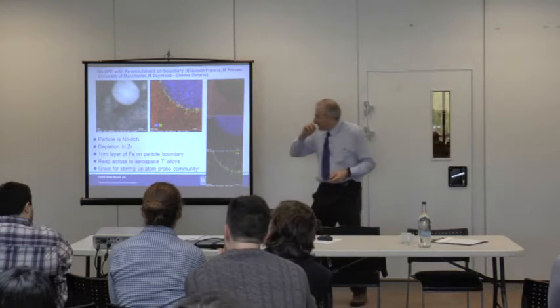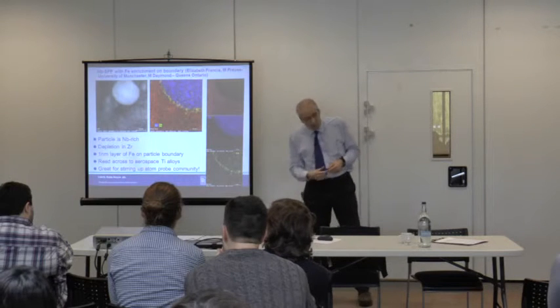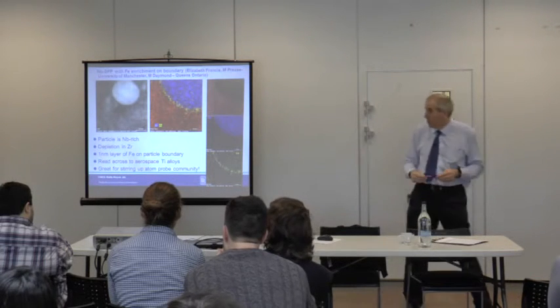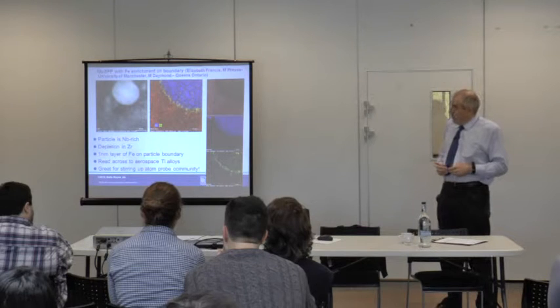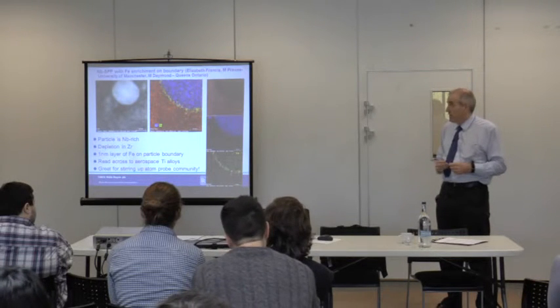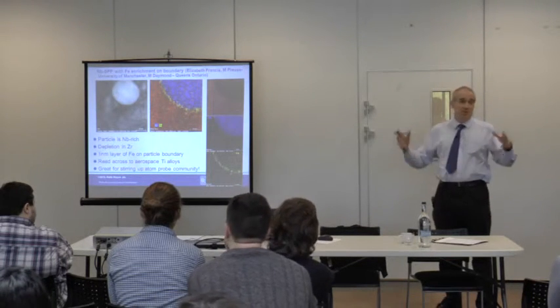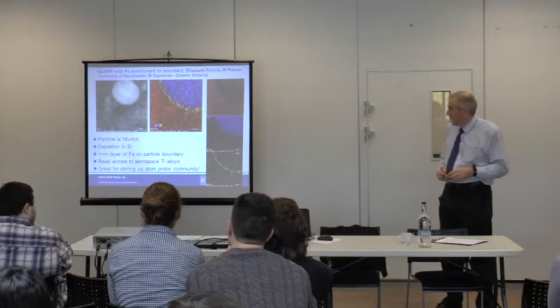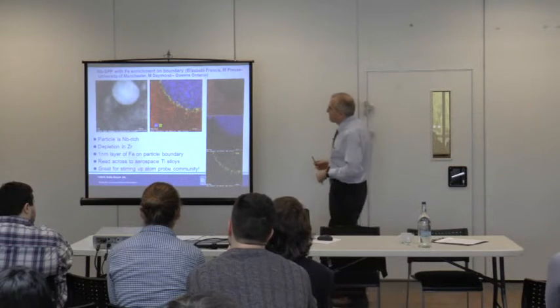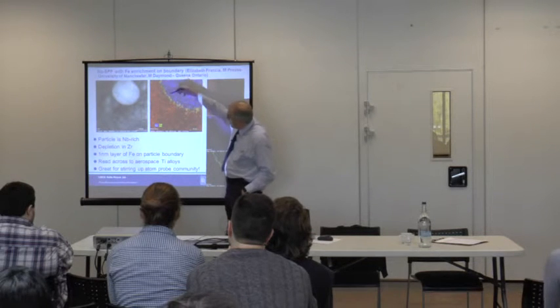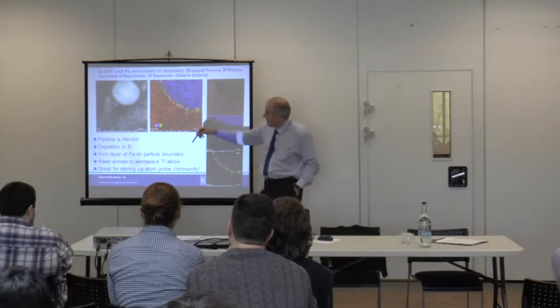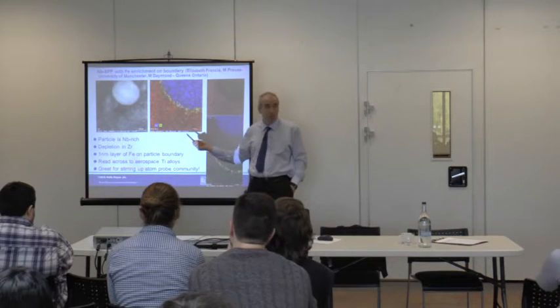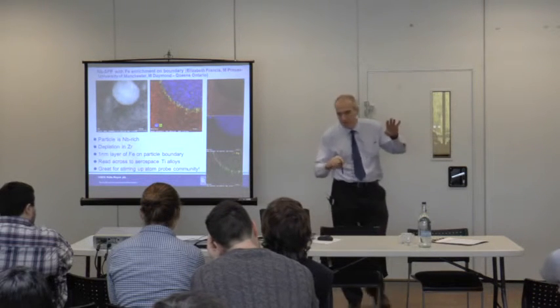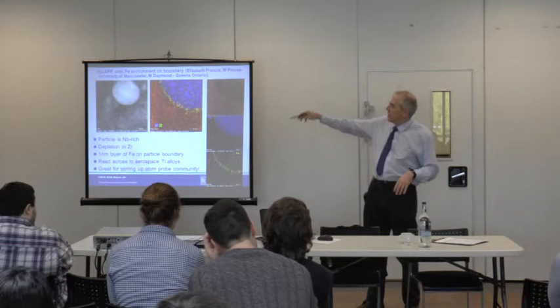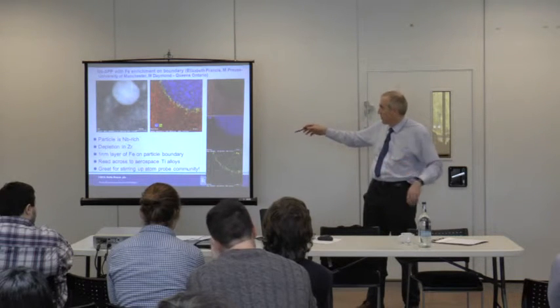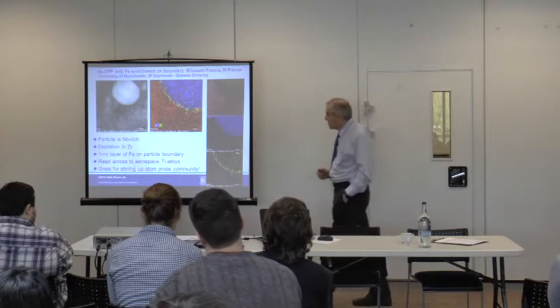So other things you can do, this is a little bit on nuclear. One of the things you find there is that things don't work quite the way you expect. So iron in zirconium moves around as an interstitial, which isn't what you'd expect because it's a damn great big atom, and it moves like blazes. So it's going really fast, and what you can see here, they can actually image iron moving down boundaries, and that's a 4 nanometer length scale bar. I should mention the groups. They should all be on the slides, the people that I'm interacting with on this, where we've got programs running. This is Michael Preuss and co at Manchester.